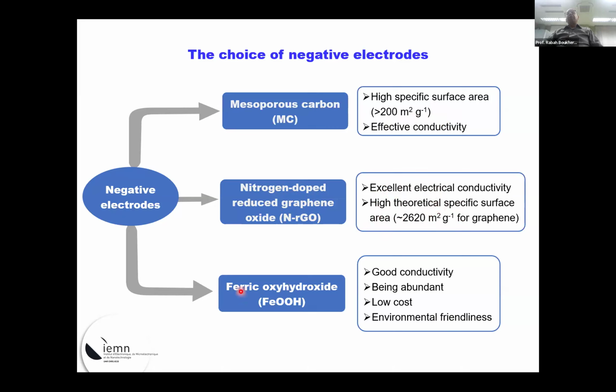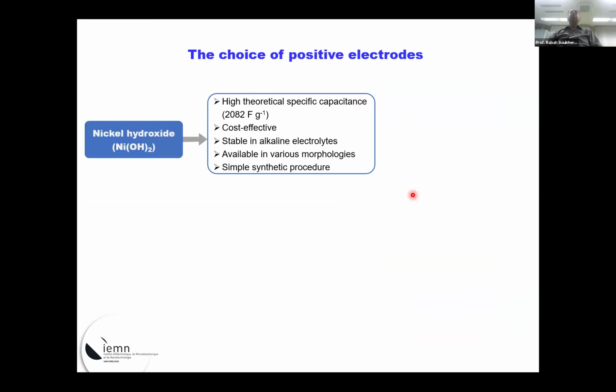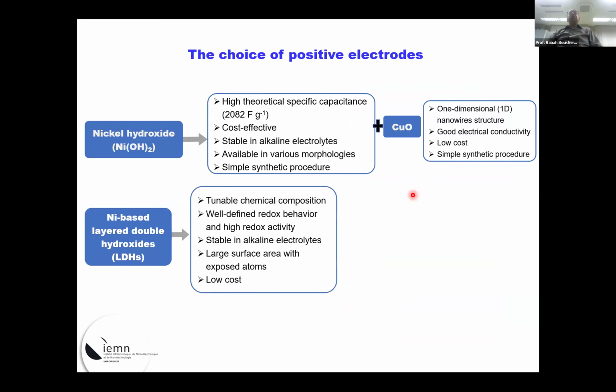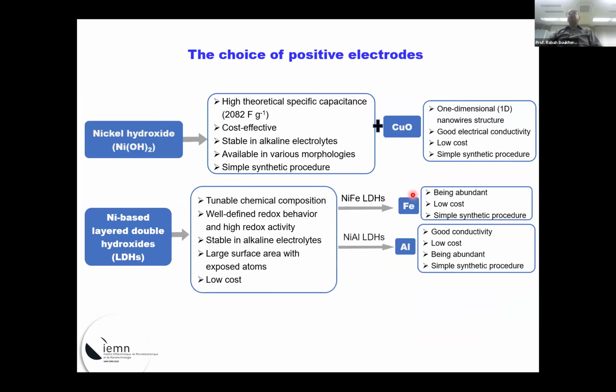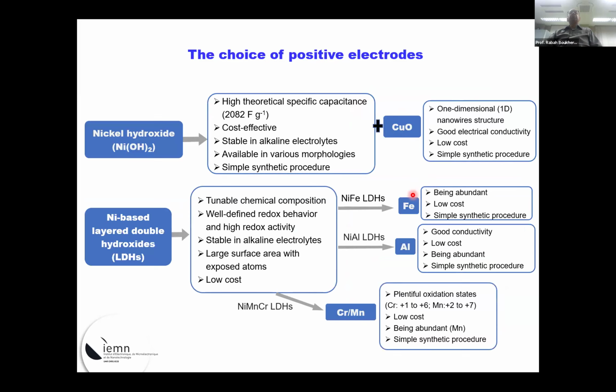You have ferric oxyhydroxides. They have good conductivity, they're abundant, low cost, and environmentally friendly. So this is also interesting, but it doesn't exhibit as high a capacitance as you can record from carbon-based materials. For the positive electrodes, as I showed in the previous example, it's essentially transition metal-based, and specifically nickel-based. This is quite available, and it is also used very nicely in electrochemistry because it can sustain really good stability. That is really important compared to many other materials.